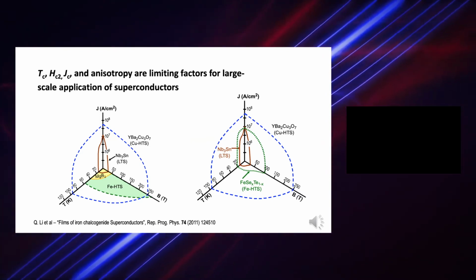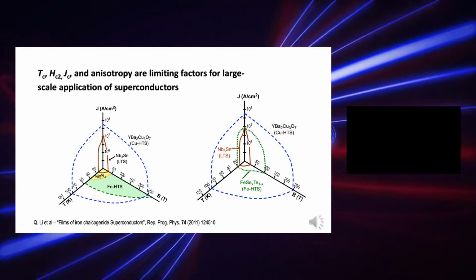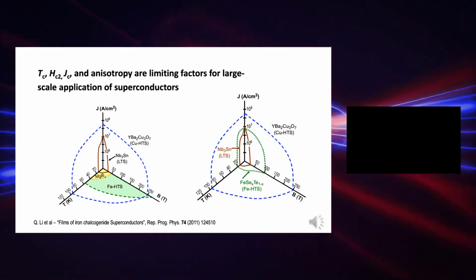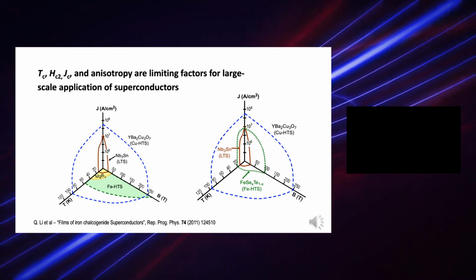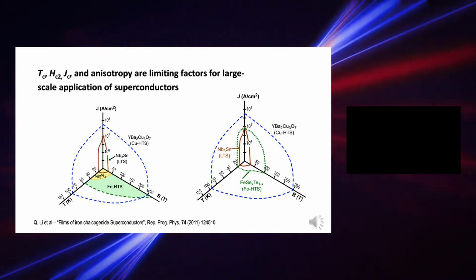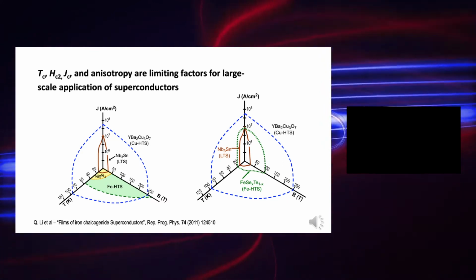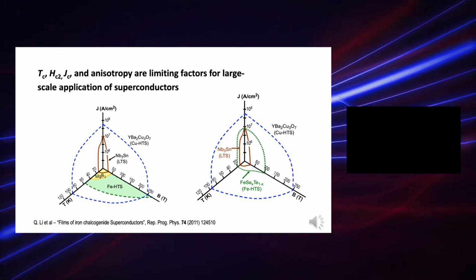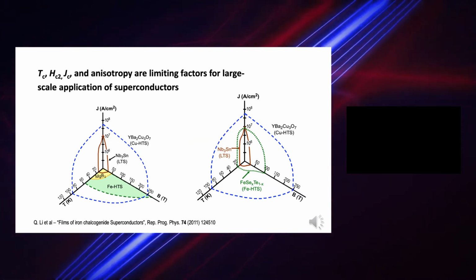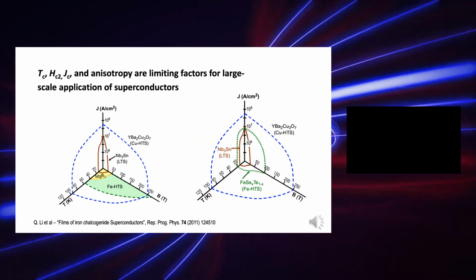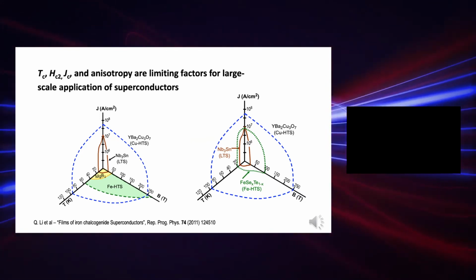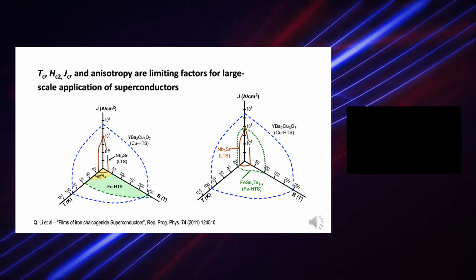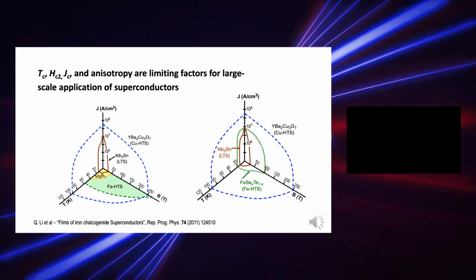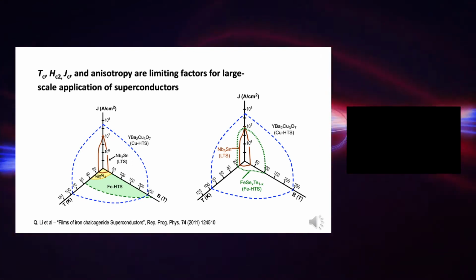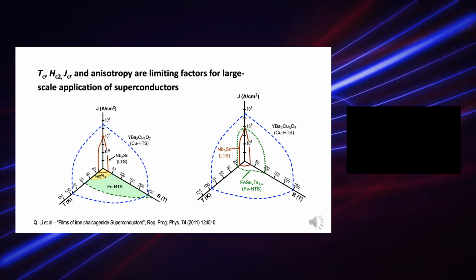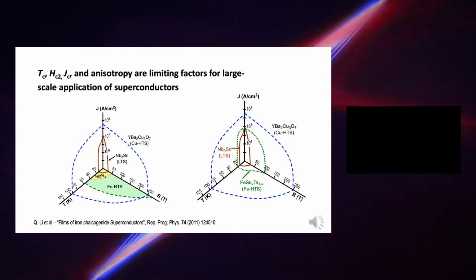More than a decade ago, I showed this plot, which made a comparison of these critical parameters for high TC cuprates, low TC materials, magnesium diborides, and iron-based superconductors. The potential of iron-based superconductors for large-scale applications is clearly seen for its very high upper critical field. At that time, the development of films, tapes and wires was at an earlier stage. Now we have reports showing that iron-based superconductors can have critical current densities above 10 megaamps per centimeter squared. And this is shown in the revised figure on the right-hand side.